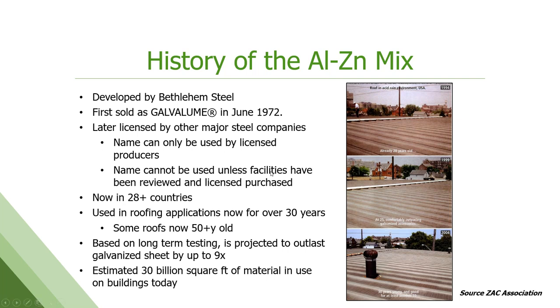What we're seeing now, since they put some roofs out in the 60s before they commercially were selling it in 1972, is that we've got close to 50 years of real world exposure on this product now, and it's looking very, very good. Everyone was going to be happy with 20 to 30 years originally, and it's proving to be much, much better than that. You can see the pictures on the right here, in an acid rain environment, so sort of a harsh environment back east. 20 years looks good, 25 looks good.